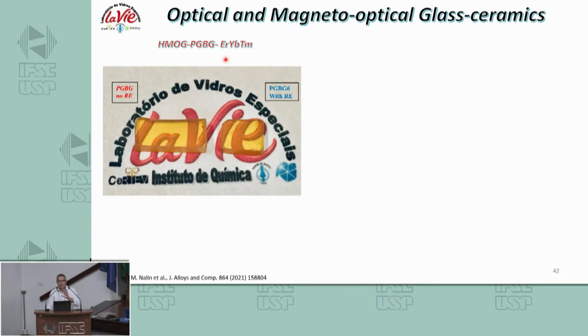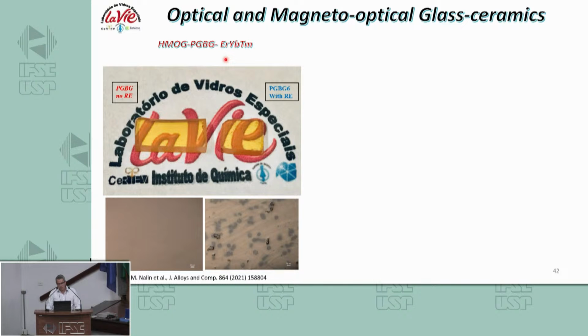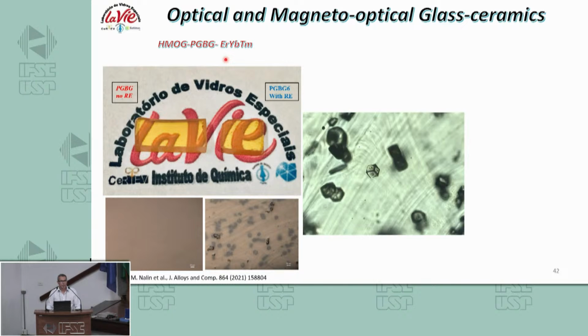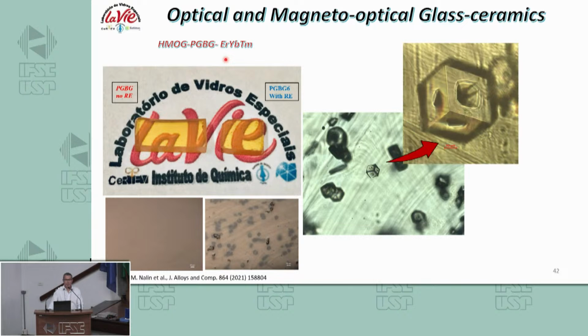So I was using this glass to operate in the infrared. And then one student of mine came to me and showed me this picture. I have a problem. I have a cubic crystal inside the glass. See? Of course, come back to the lab and do it again. And some time later, he comes and shows me again the same picture. I have the same crystals. Something's wrong. Or not. So now we are playing with the composition of this glass and producing crystals using the